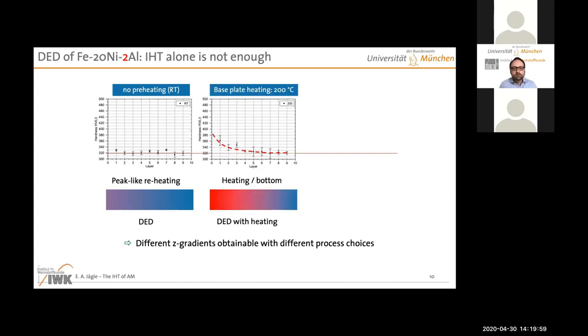One kind of heat input is base plate heating. So we stick a 200 degree base plate underneath our substrate plate, and we basically have DED with this additional little heated bed at the bottom. I mean, 200 degrees is not much, but you already see a slightly higher hardness at the very bottom layers, and then a gradual decrease as you go up. Why a gradual decrease? Well, both because the temperature will drop towards the top. I mean, the base plate is at the bottom, so the top will be a little bit cooler, and also the time spent at the 200 degrees or at the 180, 150 degrees is less as you are at the top of the sample compared to the bottom. So you have a slight decrease.